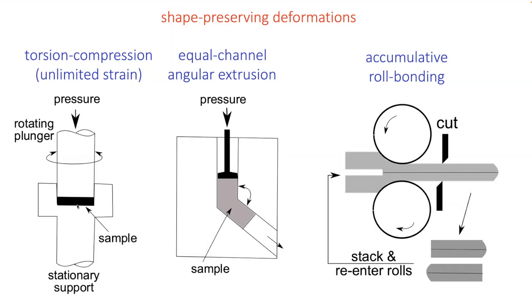But the obvious disadvantage is that you produce a very small sample. Then we have equichannel angular extrusion in which you force a piece of steel through an angle, and that introduces redundant deformation inside your material. When it comes out you can repeatedly put it through this process and accumulate plastic strain, once again getting a refined structure.